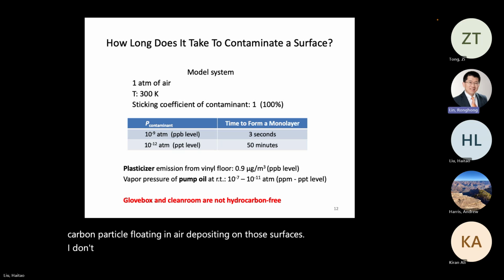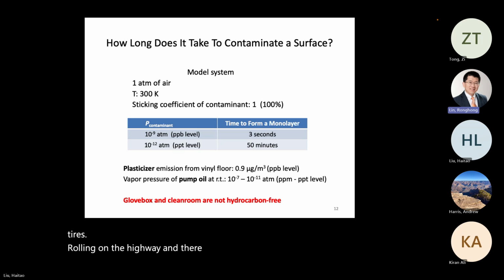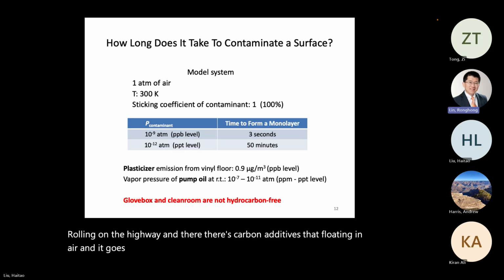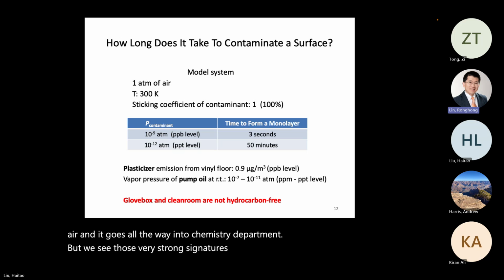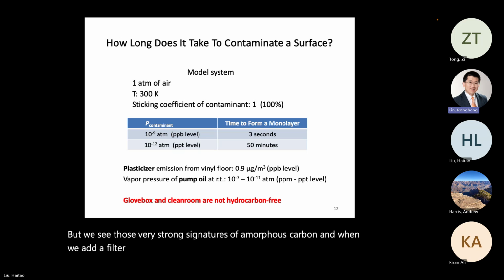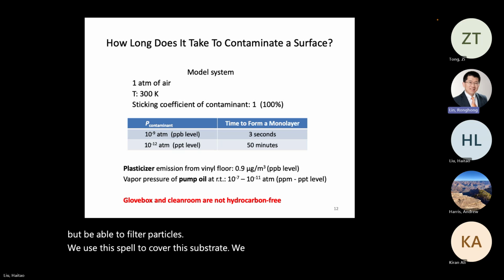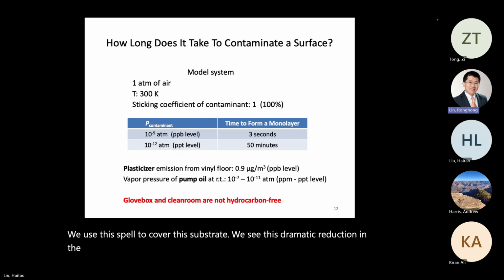I don't know exactly where they come from. Might be coming from the tires rolling on the highway, and there's carbon additive that's floating in air, and it goes all the way into the chemistry department. But we see those very strong signatures of amorphous carbon. When we add a filter that is never going to be able to filter molecular species but is able to filter particles, and use it to cover the substrates, we see a dramatic reduction in those Raman signatures. So it seems to suggest there is particulate matter on the surface, in addition to molecular material.